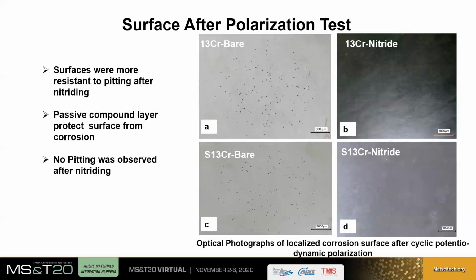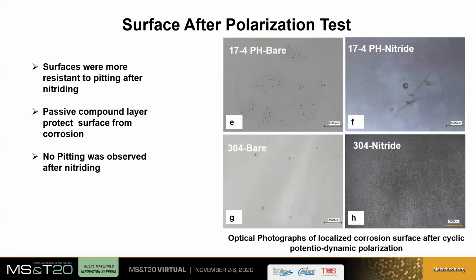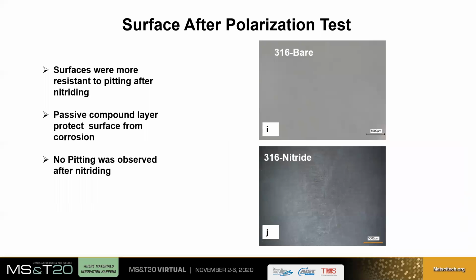Further microstructural examination was carried out on untreated and treated samples after the corrosion test. We can see the untreated surface has many corrosion pits after the polarization test, whereas the treated surface was not susceptible to any kind of pitting. We have seen this for 13 chrome and super 13 chrome material. These samples look black and dark in color because of the nitrocarburizing process, but no pits were observed. Similar behavior was observed for 17-4 PH, 304 and 316 stainless steel. The untreated surface of 316 stainless steel shows some microscopic pits at high magnification, whereas no pitting was observed after nitriding.